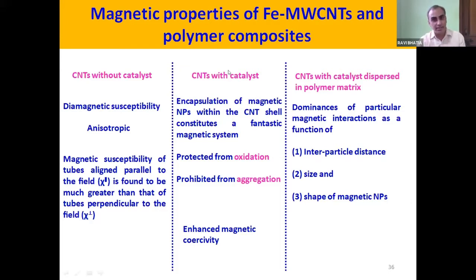When you have CNT with iron, cobalt, or nickel, it gives a very interesting and fantastic system in which oxidation and aggregation both are taken care of. Generally, the magnetic particles, if they are not capped with any other reagent, get oxidized and agglomerated. So these two problems are solved when the encapsulation is happening within the CNTs. Now the same CNTs, if they are mixed with a polymer and distributed homogeneously, there could be interesting features, which we will see whether we get right or not.